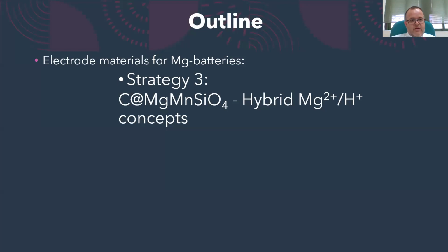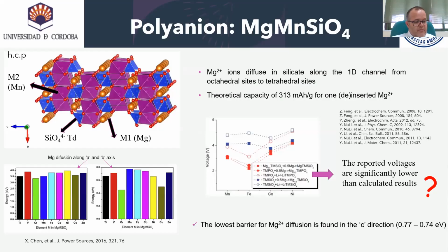Finally, the third strategy is based on the use of carbon-coated magnesium manganese silicate, and the use of a hybrid concept using protons. The magnesium manganese silicate with olivine structure consists of a distorted hexagonal close-packed framework of oxygen, building tetrahedral sites occupied by silicon and two octahedral sites. First, M1 occupied by magnesium and M2 occupied by manganese. This compound may reach a theoretical capacity of around 313 mAh per gram for one inserted magnesium.